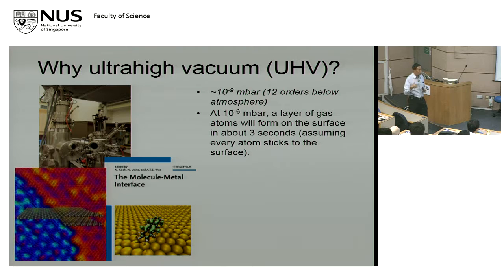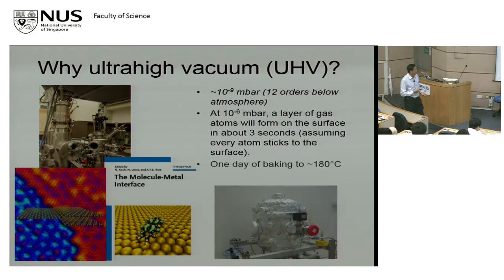Now 10 to the minus 9 is achievable. Normal turbo ion pumps that you have in your labs actually will reach this pressure, but most of the time you only reach 10 to the minus 6, and it will take a long time, depending on the pumping speed and pumping volume, before you reach 10 to the minus 9 or below. But a surface scientist will know, we quicken it by baking it. It's like an oven, we bake it.